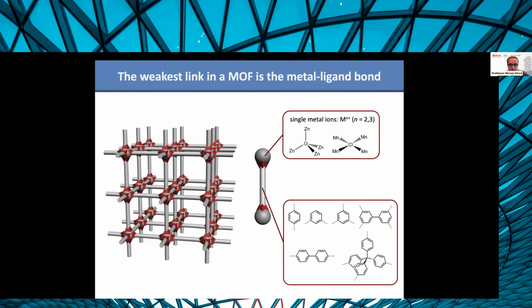So I'm going to go very basic here and say, of course, MOFs are made from SBUs and organic ligands, but really I would argue that the most important connection in any MOF is the metal ligand connection. That is the weakest bond. It's what defines the thermal and hydrolytic stability of MOFs. So if you look at a zinc-oxygen bond, it's actually a very ionic bond. It's going to be very hydrolytically unstable. How can we make that bond more stable?